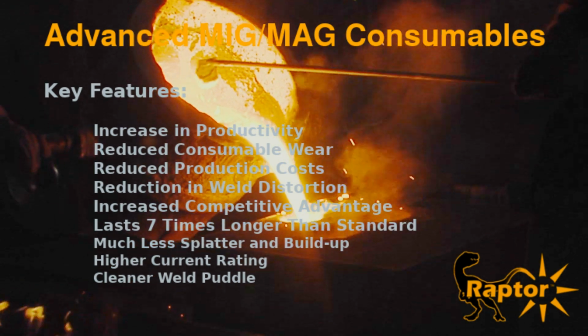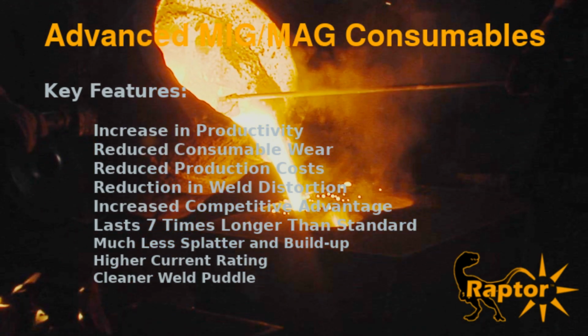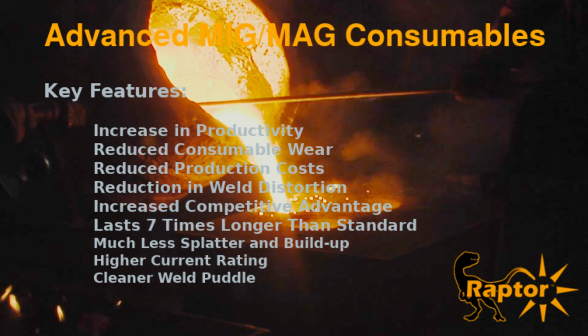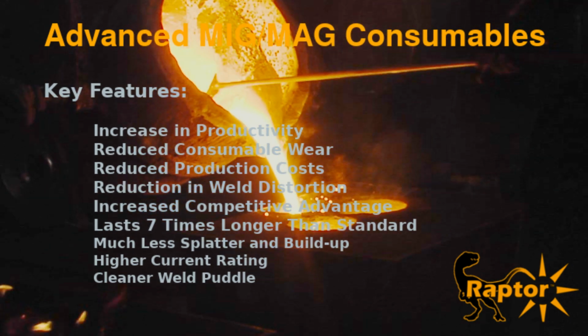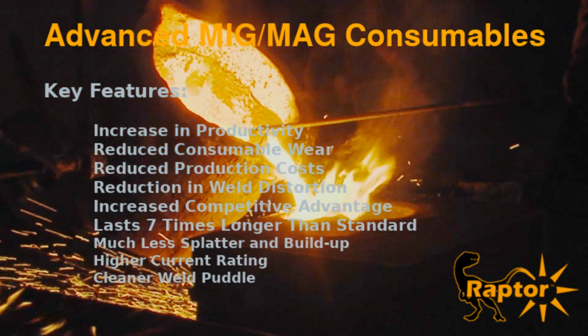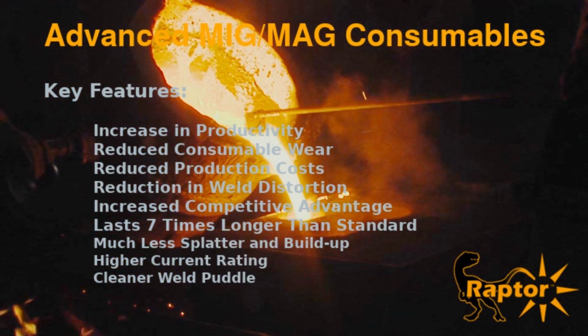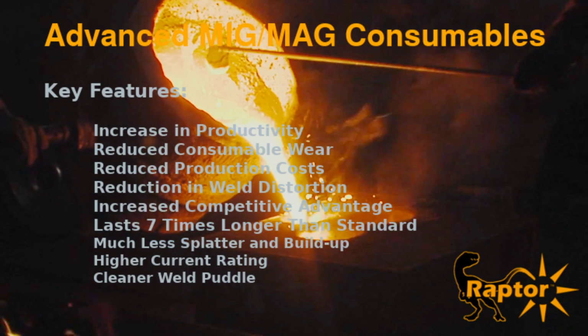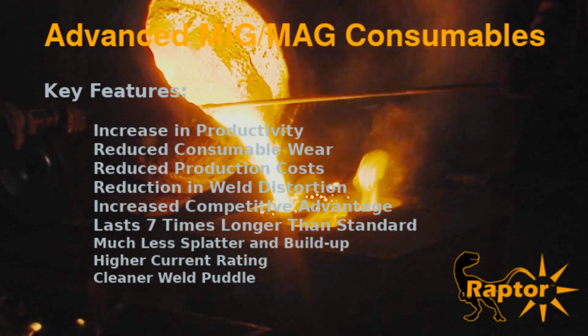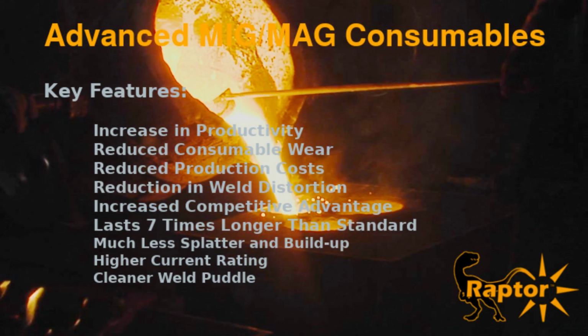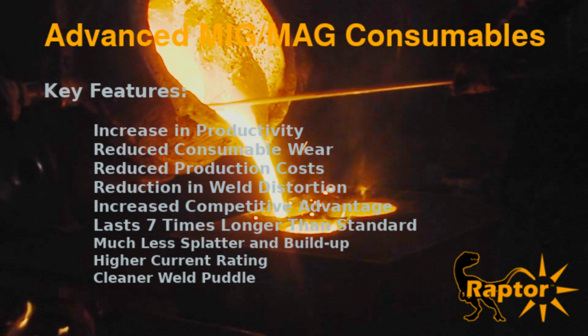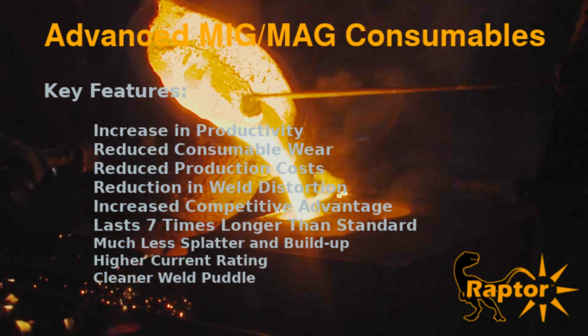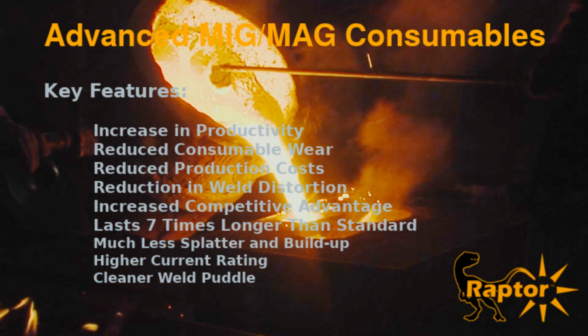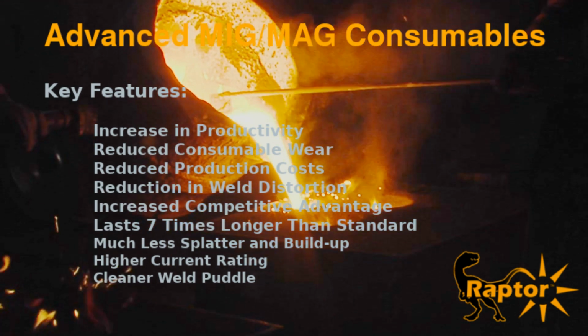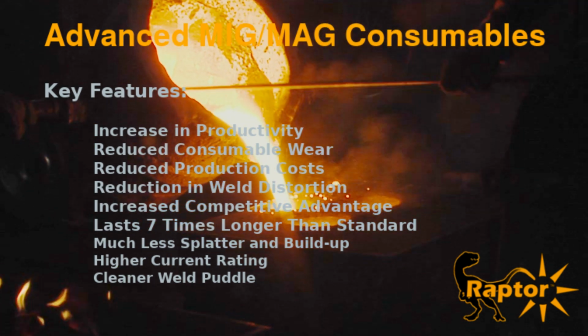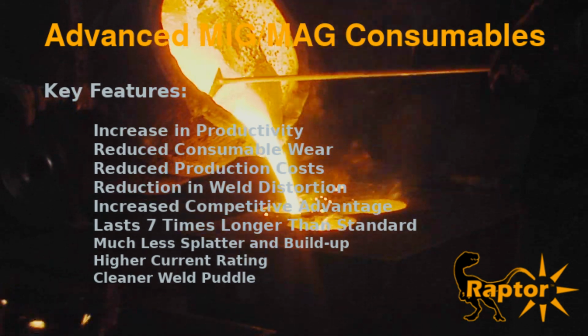Raptor offers MIG Endurance consumables which feature silver plating combined with special alloys. The contact tips are designed to enhance MIG welding operations. Significant manufacturing attention is paid to contact tips, because these consumable parts are most frequently replaced, and also influence the welding quality and speed to a great degree. An example of MIG Endurance unique innovation is contact tips, plated with pure silver to reduce splatter issues, and extend the life of parts by as much as 7 times.